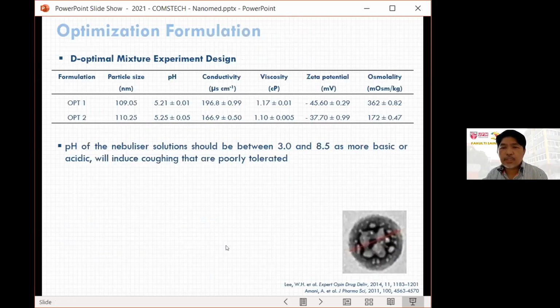So from here, we did a lot of things that we optimized. And from the optimization, as you can see, the nano emulsion droplets that we managed to get are basically spherical in shape, and the size obtained is around 100 nanometer, as you can see from this TEM micrograph. And it's also correlated with our measurement from the Zetasizer.